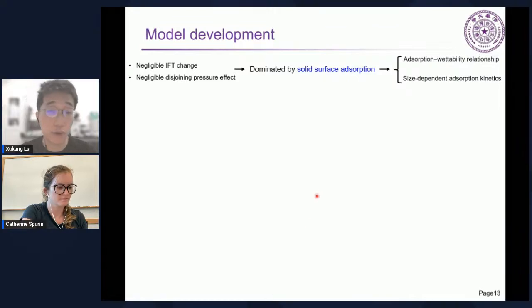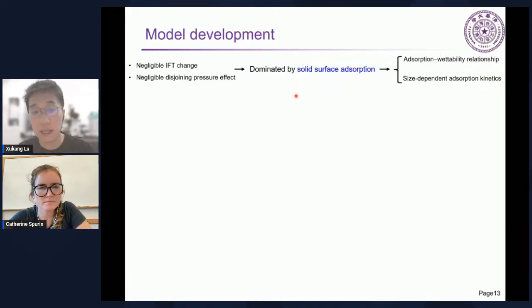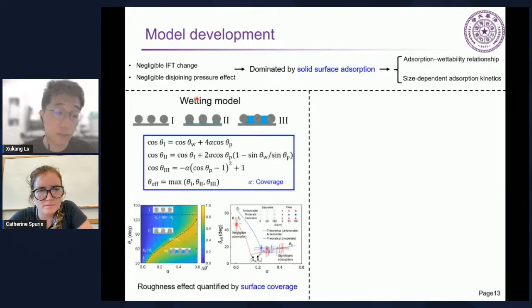And then we try to predict it and quantify it. The first step is to exclude all the other factors, so we make sure that solid surface adsorption dominates during this process. For the model development, the first part is the wetting model, about the relationship between the wettability change and how particles are distributed on the surface. Finally, we can extract the relationship between the apparent contact angle and the surface coverage, which is measurable from experiments, as we introduced before.